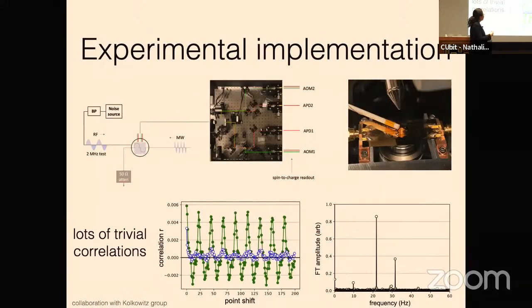Okay, so we set out to do this spin to charge and actually implement this correlation sensing, and it's relatively straightforward. You just have to build a dual channel confocal microscope, and then find some way to mount your diamond and apply some other noise signal with an antenna. And the thing that we found immediately, I'm saying this as a community service in case anyone wants to actually build one of these experiments, is that you measure a lot of trivial correlations basically right away. So we did the experiment and we got this data point up here and we were like, great, we see a correlation.